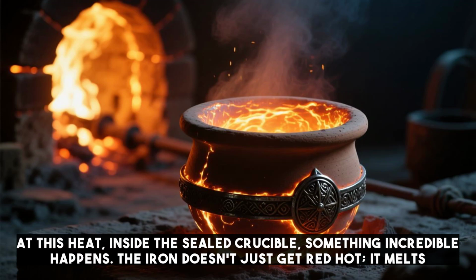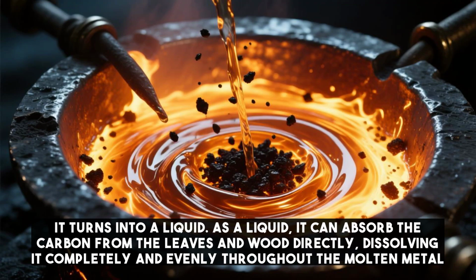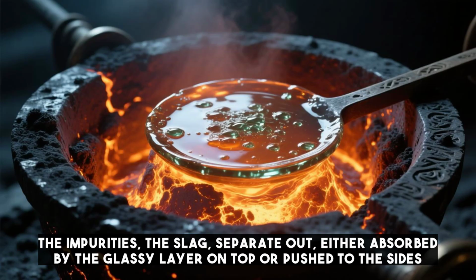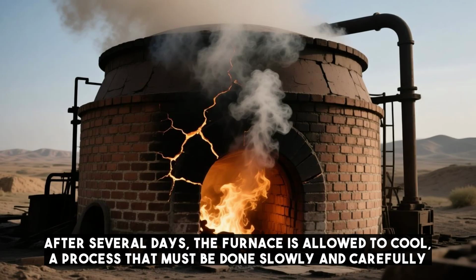At this heat, inside the sealed crucible, something incredible happens. The iron doesn't just get red hot, it melts. It turns into a liquid. As a liquid, it can absorb the carbon from the leaves and wood directly, dissolving it completely and evenly throughout the molten metal. The impurities, the slag, separate out, either absorbed by the glassy layer on top or pushed to the sides. After several days, the furnace is allowed to cool, a process that must be done slowly and carefully.